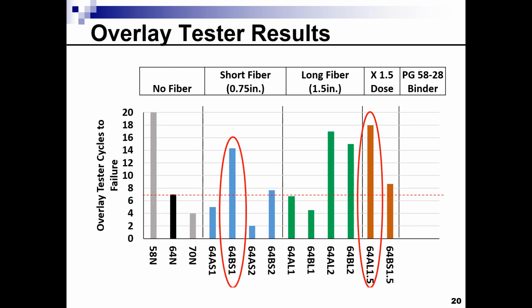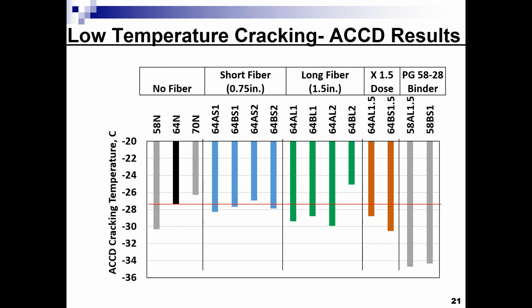We also did the overlay tester, and here what we have seen is that the optimal, based on the CTindex, seems to be the short fiber B with the recommended dosage. For fiber A, the optimal is still the long fiber, but it should go to 1.5 times the dosage, as you can see here. But even with the one dosage, it seems to be significant, or it seems that it is doing some improvement here.